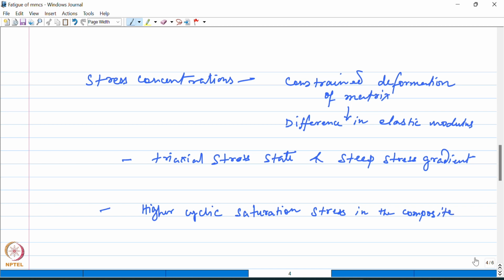What this essentially means is that stresses required for a certain amount of deformation are higher in the composite compared to that in the unreinforced matrix. So this is what we have seen before also for the 2219 aluminum titanium carbide composite.